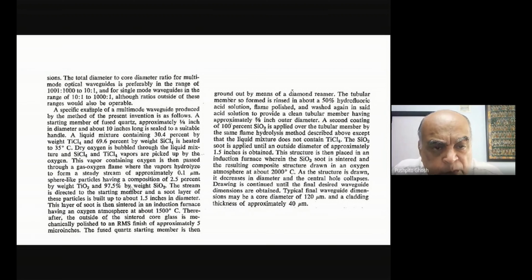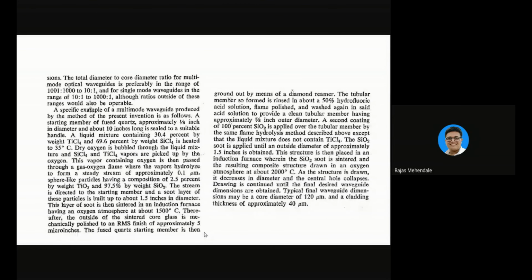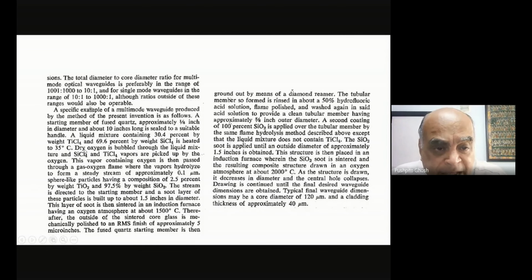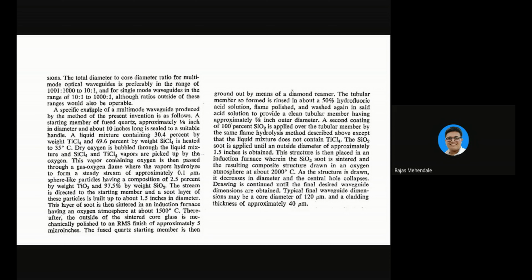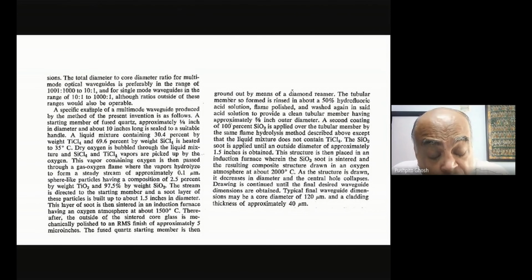It's not clear to me why, if they start with a percentage which is 30.4% and 69.6%, of TiCl4 and SiCl4, how they are actually achieving this kind of a ratio. So when we are bubbling oxygen through that liquid, as you said, they're doing the volatilization by bubbling oxygen through the liquid. So maybe that is the reason that we are getting this 2.5 and 97.5. Like the mass transfer rate is in favor of silicon chloride. Very interesting. You could be right.